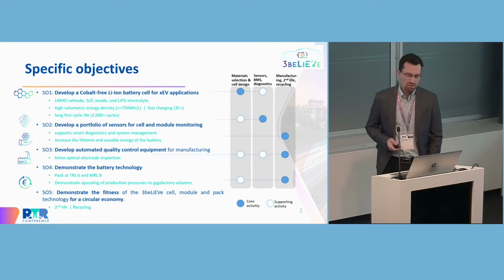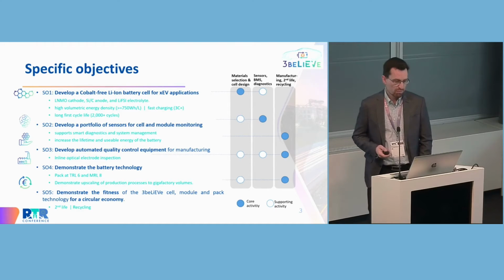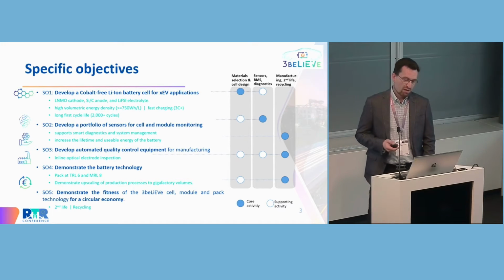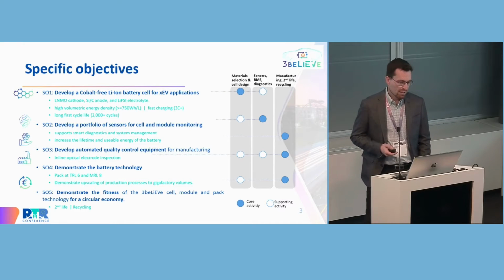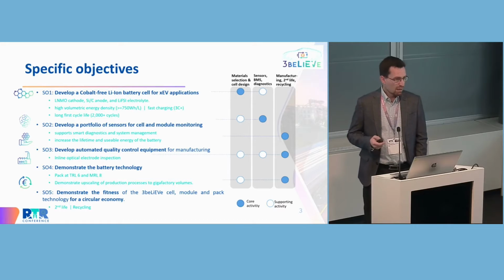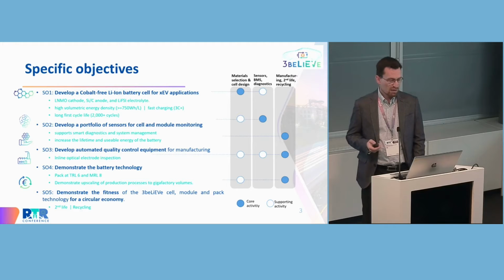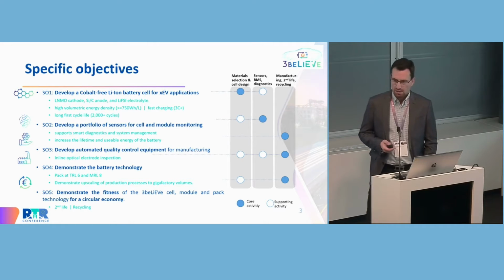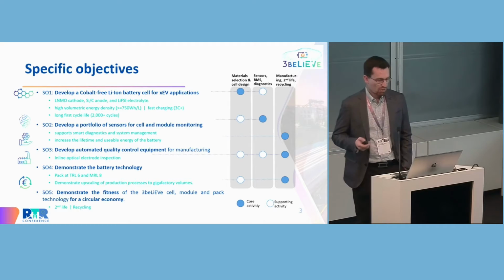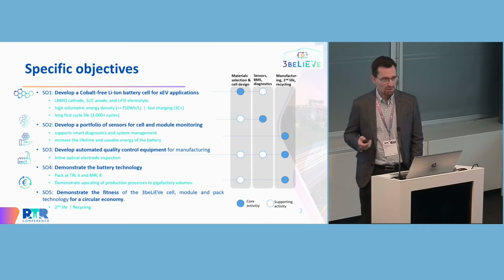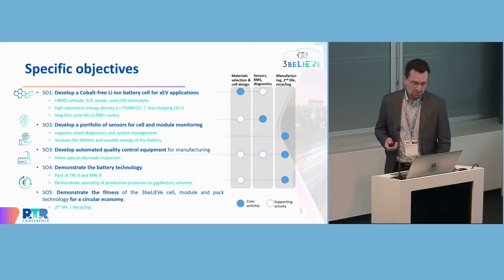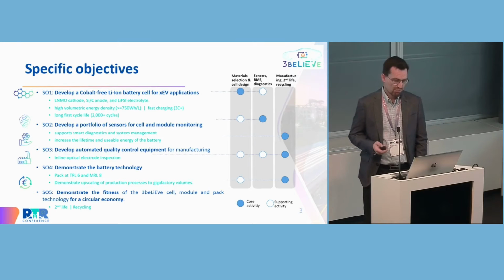So the work was clustered around 5 specific objectives. The first, of course, focuses on the cell chemistry itself, so to develop a cobalt-free lithium-ion battery for hybrid electric and fully electric vehicle applications. What we were focusing on here was to combine a lithium nickel manganese oxide cathode, a silicon graphite anode, and a high voltage electrolyte. And the performance targets were taken directly from the call, so high volumetric energy density of 750 watt-hours a liter, fast charging capability, and of course long cycle life.